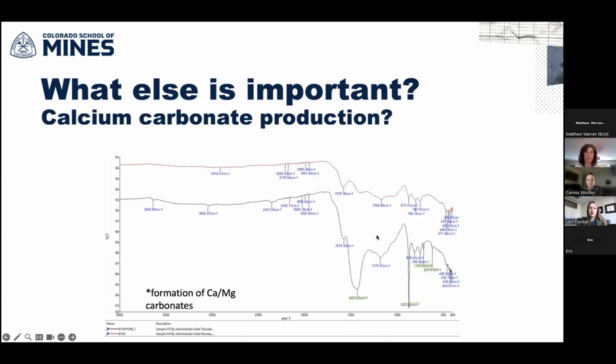So I mentioned the calcium carbonate production. This is something that's gotten a lot of attention recently with some of these greener cement technologies like CarbonCure, for example, that are promoting the formation of calcium carbonate. So there's lots of data out there indicating that if you can get calcium carbonate growth within a cement mix, you get densification. So it basically fills the pores. We have some preliminary data indicating that we do have carbonate species increased with the production of biochar. But what we're trying to do right now is to understand, is it related to the biochar itself, or is it actually producing calcium carbonate within the mix?